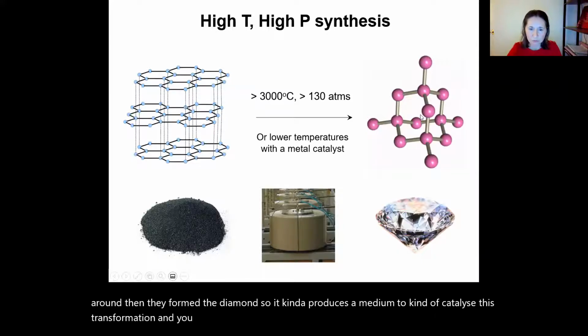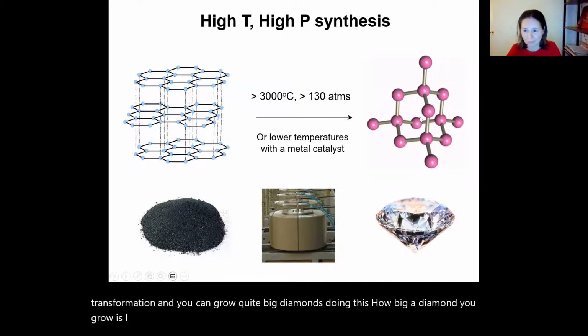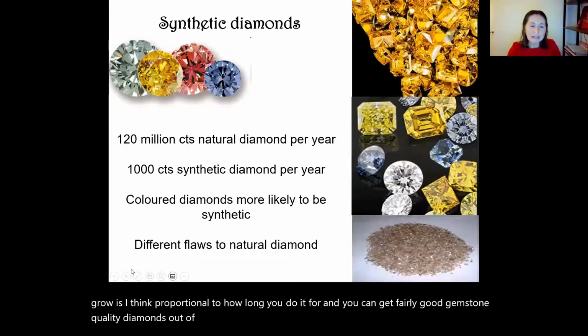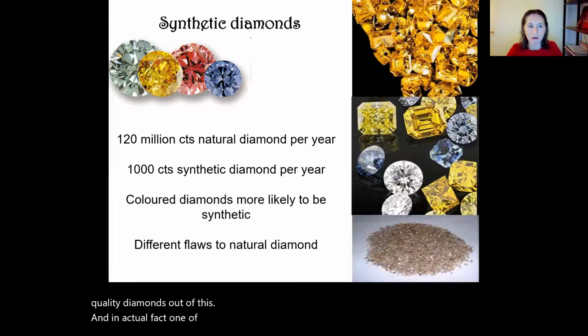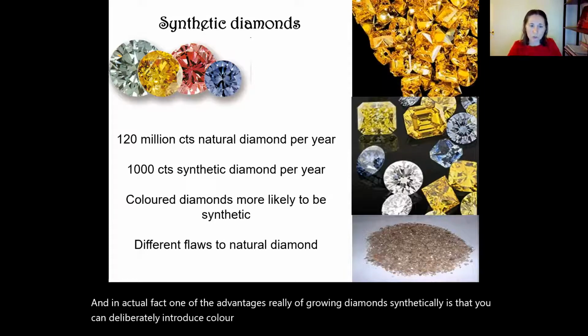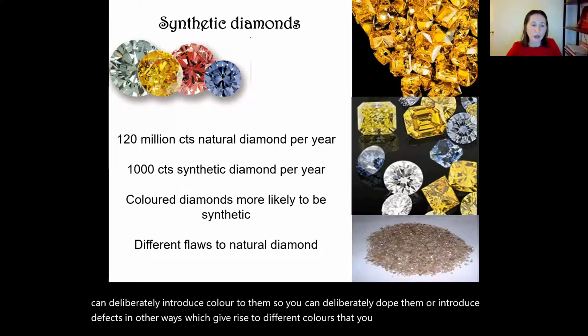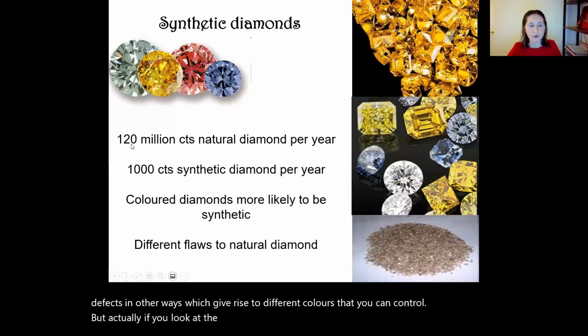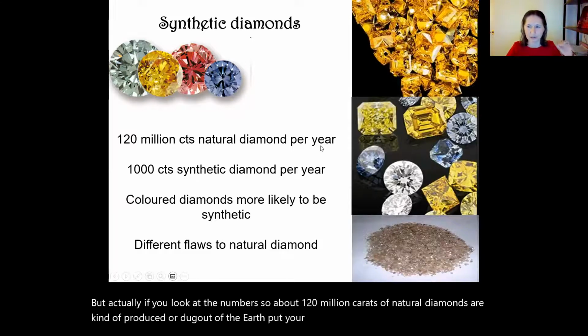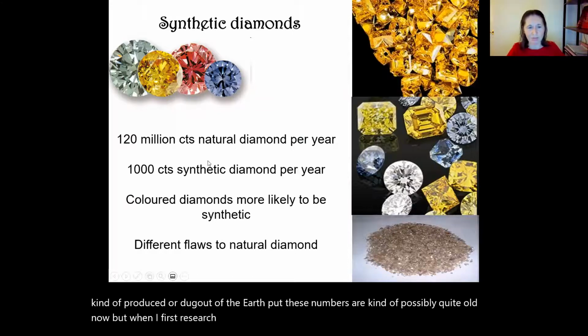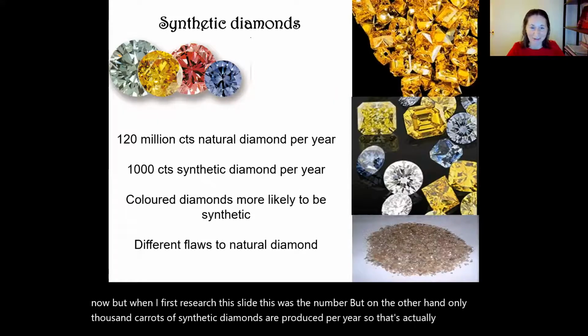And you can grow quite big diamonds doing this. How big a diamond you grow is, I think, proportional to how long you do it for. And you can get fairly good gemstone quality diamonds out of this. And in actual fact, one of the advantages of growing diamonds synthetically is that you can deliberately introduce color to them. So you can deliberately dope them or introduce defects in other ways which give rise to different colors that you can control. But actually, if you look at the numbers, about 120 million carats of natural diamonds are produced or dug out of the earth per year. These numbers are possibly quite old now, but when I first researched this slide, this was the number. But on the other hand, only 1,000 carats of synthetic diamonds are produced per year. So that's actually quite a significant amount less.